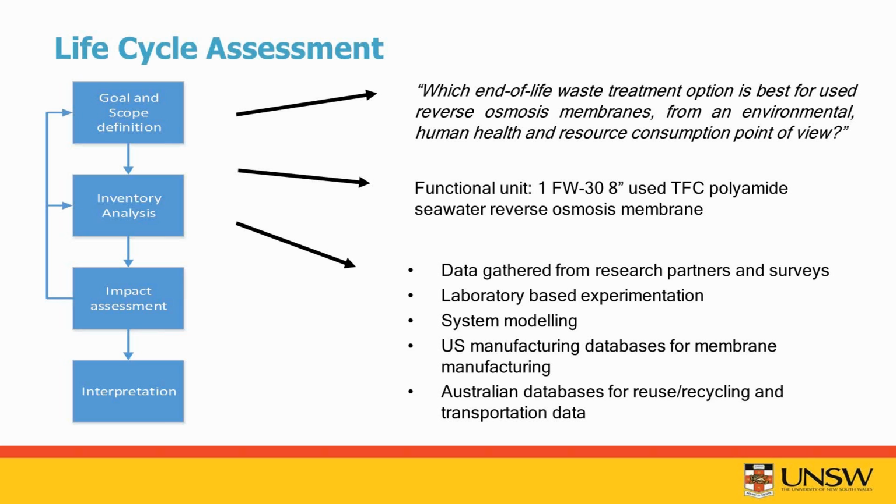So we take one RO membrane, a standardized thin film composite polyamide membrane. We generate a model around that. Life cycle assessment is only as good as the data that you input into the model. So we've been using primarily first-hand gathered data from our research partners and various industry surveys. The second tier is laboratory-based experimentation for the options that aren't already commercially used. We use our experience and our assessment for that input.